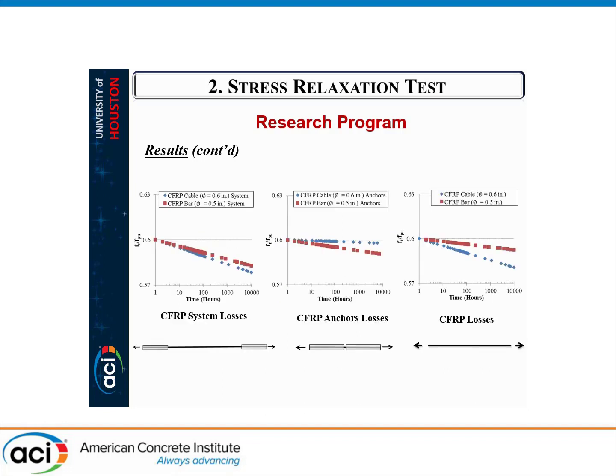So here we are showing how to subtract the anchorage losses from the total loss of the system to obtain the pure relaxation of the CFRP. At the very left graph, we have the relaxation of CFRP cable and bars at 60% initial jacking. And the middle graph is the relaxation obtained from the anchorage losses of the CFRP and cables, again at the same level of prestressing. By subtracting the anchorage losses from the losses of the system, we obtain the pure relaxation at the very right figure.